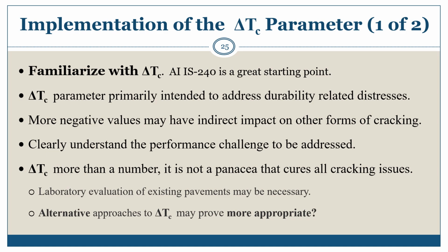Note that the delta TC parameter is primarily intended to address durability related distresses. Understand that more negative values may have an indirect impact on other forms of cracking other than block cracking. However, block cracking is the only mode of cracking that has been directly related. If you have a cracking issue, clearly understand the performance challenge to be addressed. Ensure that delta TC is the proper parameter to address the issue to be addressed. Understanding of a problem first may make the solution more attainable.